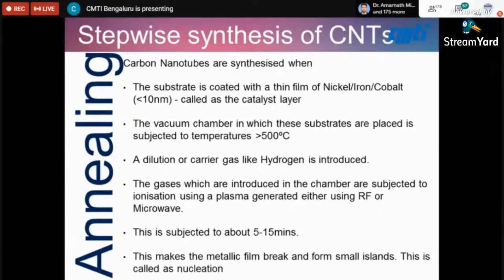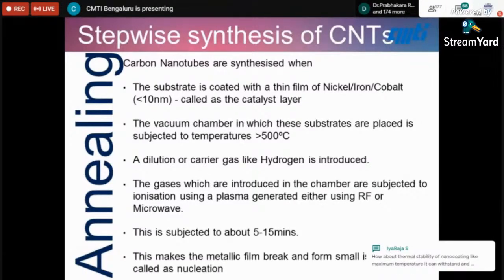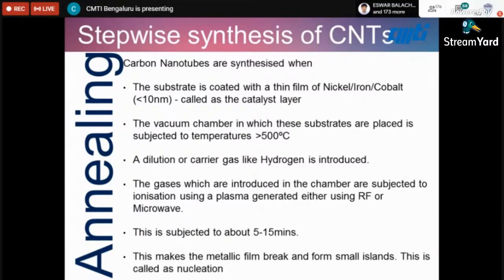The first and foremost thing is, you will have to deposit a thin layer of a metal like either nickel, iron, or cobalt, preferably less than 10 nanometers. This is called the catalyst layer, and you deposit it using a sputtering system. Then you take it out of the PVD system and put it into a vacuum chamber, preferably a PECVD, and then you heat it to, let's say, about 500 degrees. You introduce hydrogen and ionize it using a plasma.